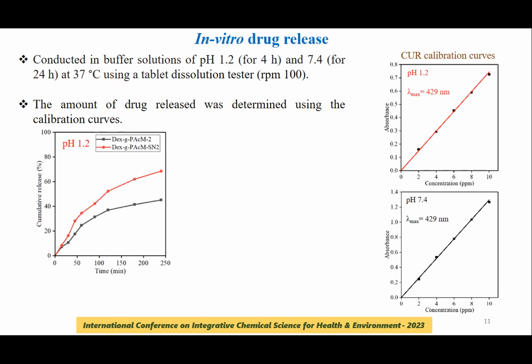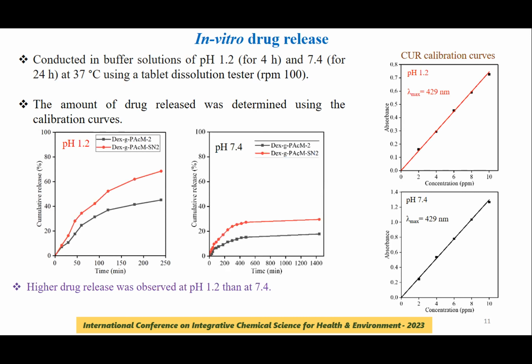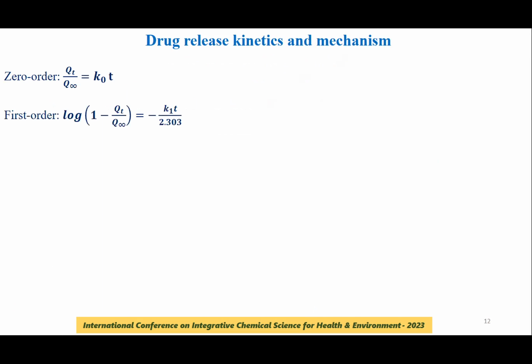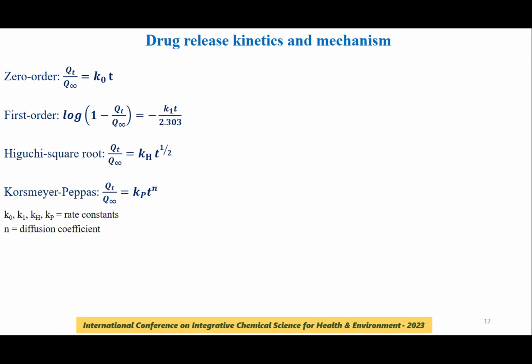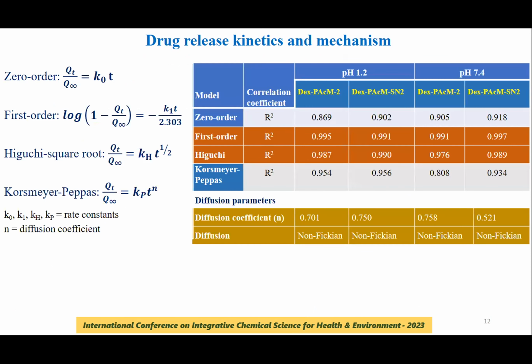The results show that higher drug release was observed at pH 1.2 than 7.4, and the hydrogel nanocomposite showed higher drug release than its parent hydrogel. These results agree with the results for swelling and drug loading. Kinetics of drug release and mechanism were also studied using various models, and the drug release kinetics followed first order kinetics based on correlation coefficients, meaning R square value. This revealed that the drug release not only depends on the concentration of the drug, but also on the nature of the delivery system.